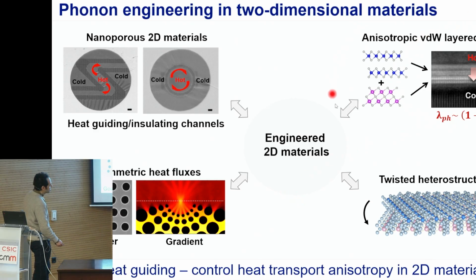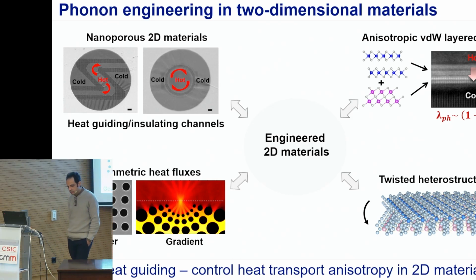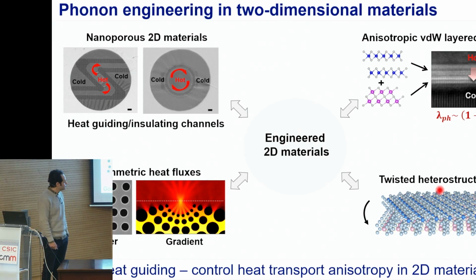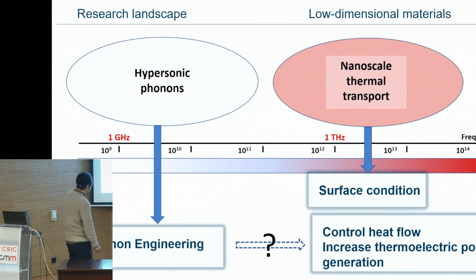And if we go to smaller scales, we are working with superlattices and heterostructures. So we are growing with different epitaxial techniques, molecular beam epitaxy and atomic layer deposition, these kinds of atomic layers on top of each other in order to control, in this case, the cross-plane heat dissipation. And of course, always a good method is the twisting. I don't have a lot of results to show you about this, but it's also something interesting, because by twisting the 2D materials, actually we create this lattice mismatch between the atomic layers, and it's something interesting to be investigated.